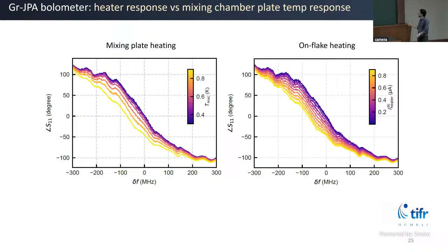And then we also test this idea that first you can heat the device by changing the temperature of your fridge, because you have heaters on the fridge that you can increase. Also, you can change the on-flake heating by sending more current through this heater port. And we see a nice correlation that both show a similar trend: when you heat up, the frequency goes down. And roughly, just to give you some numbers, if you send 1 microamp of current, that raises the junction temperature to around 1 Kelvin.